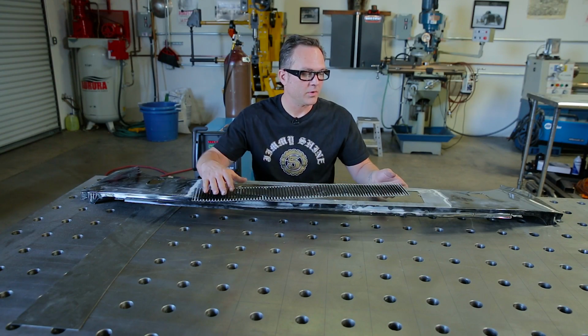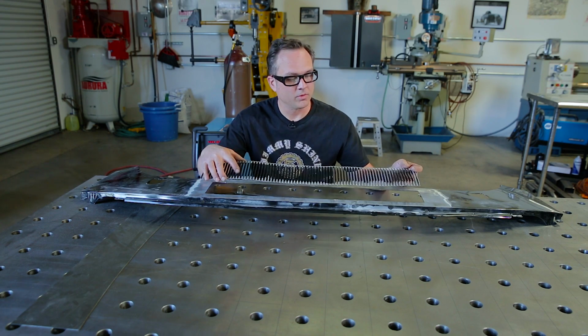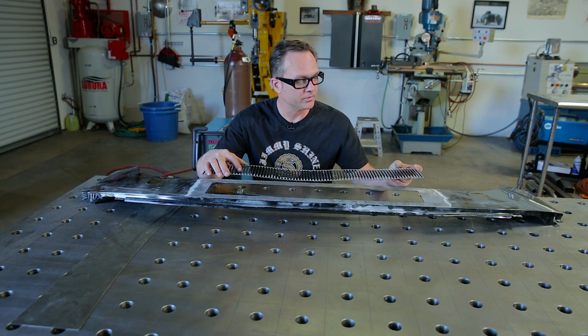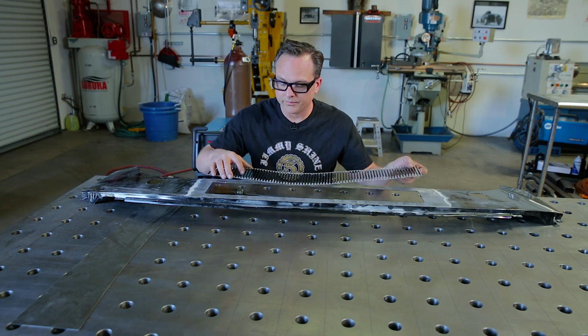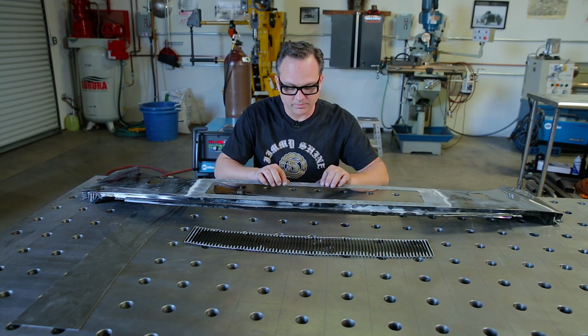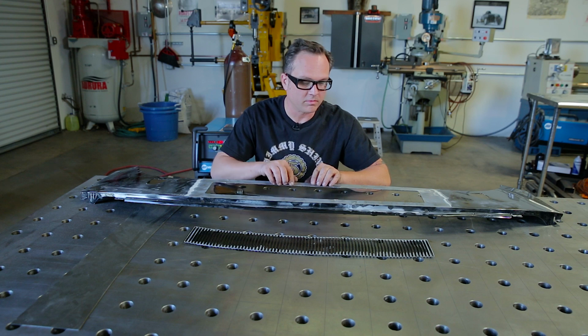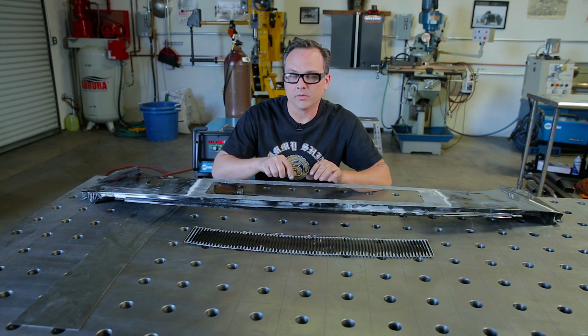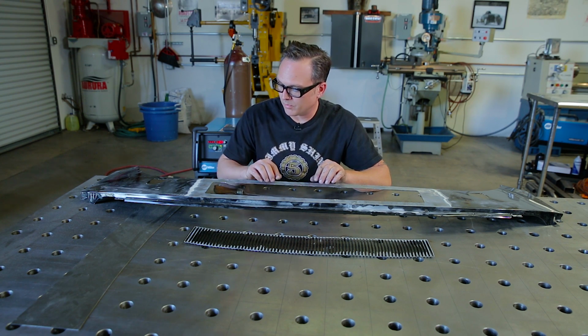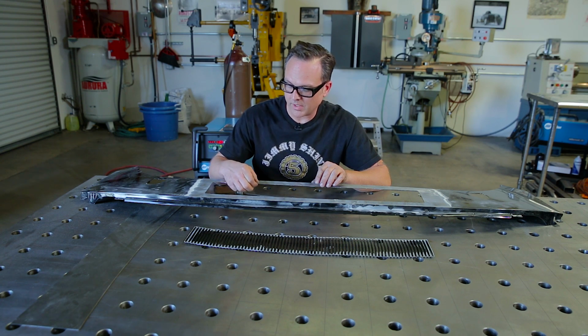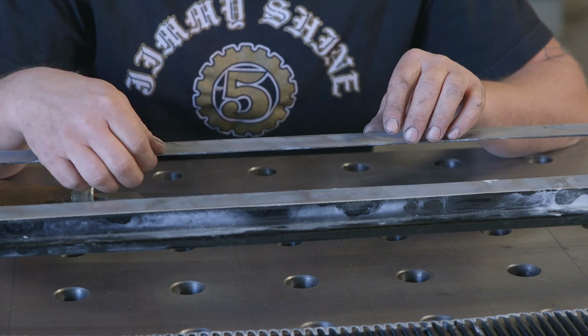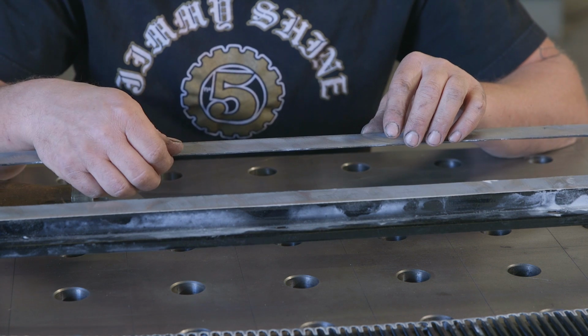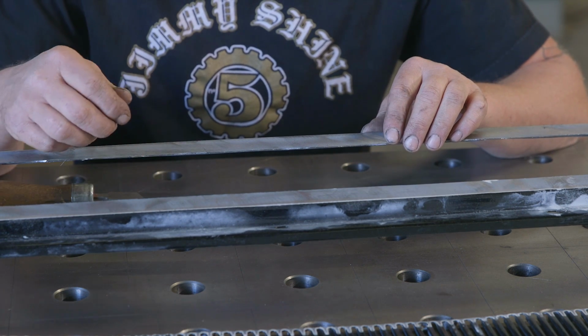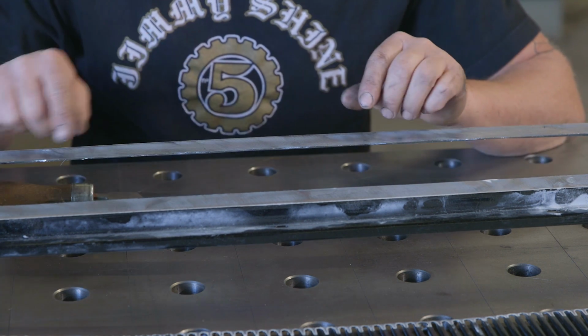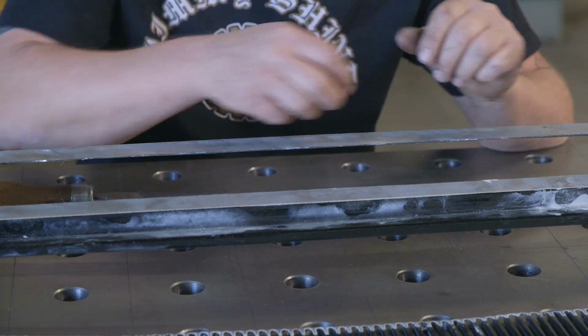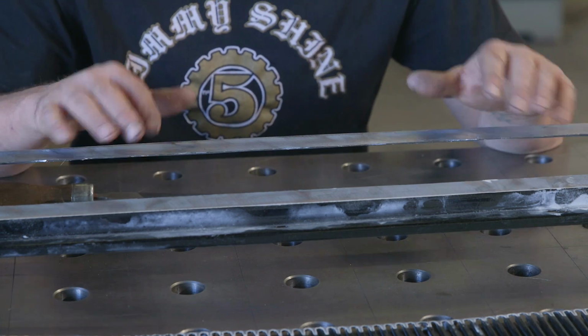So using an abrasive cutoff wheel, cut out the old sectional louvers, if we want to call it that. There are different ways of cutting, but cutting with a saw or abrasive cutoff wheel, there are always burrs left, which we want to remove because this thin metal often gets burned because of the heat, and when it burns, it's oxide, which can contaminate our welds. Plus, we want this edge to be really smooth for when we scribe our new piece to put in.